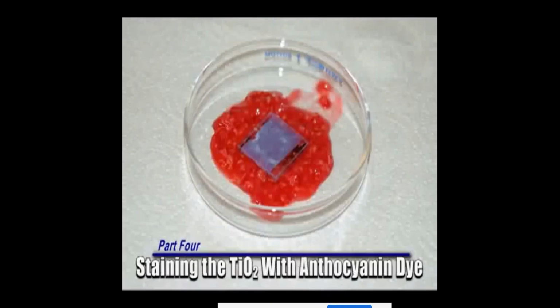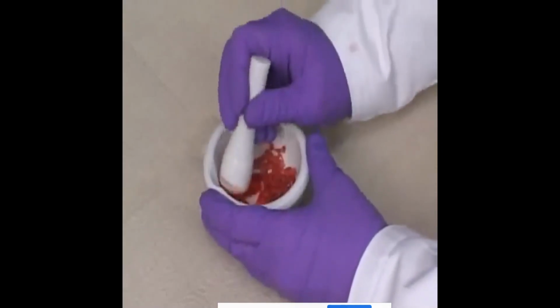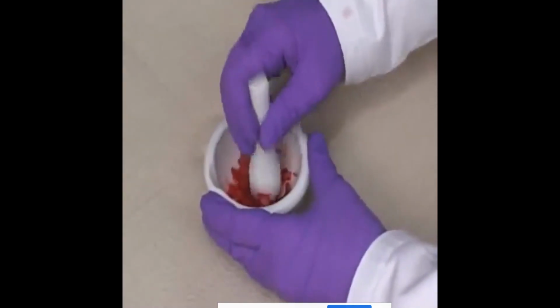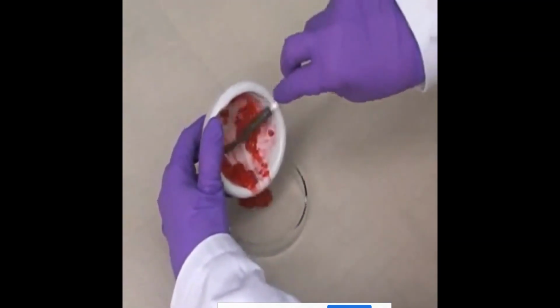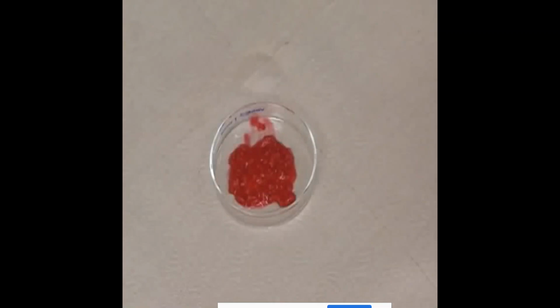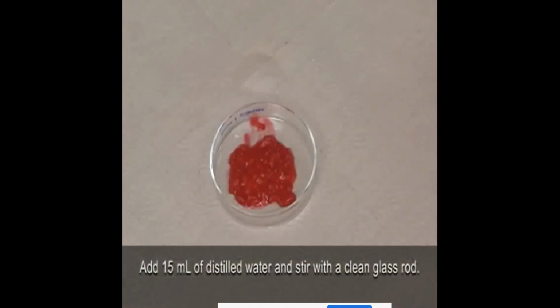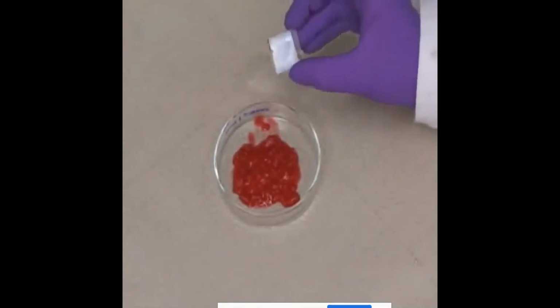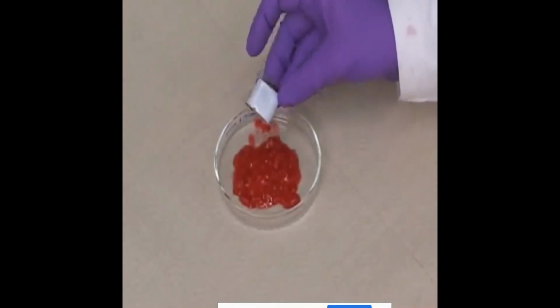Part 4. Staining the titanium dioxide with anthocyanin dye. Step 1. Use a clean mortar and pestle to crush 3 to 4 berries. Transfer the crushed berries to a petri dish. Step 2. Add about a tablespoon of distilled water to the crushed berries and stir with a clean glass rod. Step 3. Place the slide face down into the berry mixture so that the titanium dioxide coated section is submerged in berry juice.